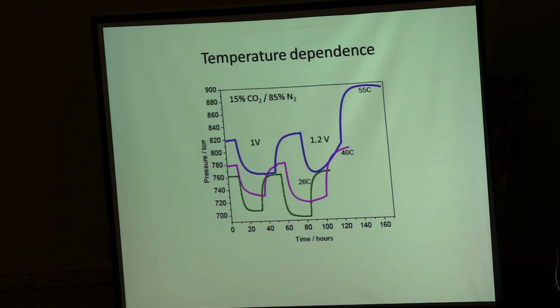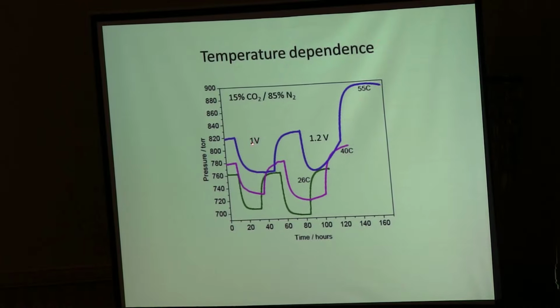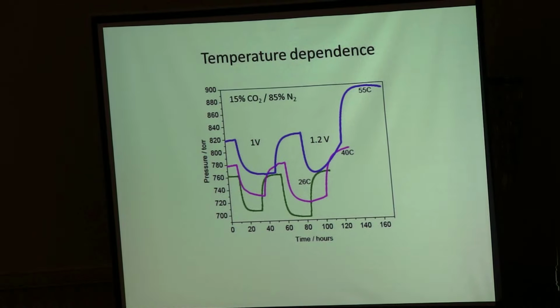Finally, we were also interested in the temperature dependence of the supercapacitive swing adsorption effect. So we measured our pressure changes at 26, 40, and 55 degrees Celsius at 1 volt and 1.2 volt respectively. You see from the curves that the supercapacitive swing adsorption effect is fairly independent from the temperature. At 1.2 volt, you see, however, something unusual, because at higher temperatures, after the pressure goes down, it begins to go up, and this is more pronounced at the highest temperatures.